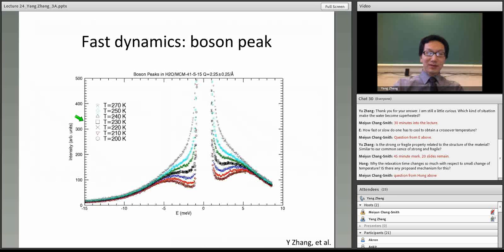Another interesting phenomenon that happens above the glass transition temperature is the so-called boson peak. For many crystalline materials, the phonon density of states g(ω) follows ω squared. So if you divide g(ω) by ω squared, you should have a straight line. For many glassy materials, if you measure the phonon density of states, you'll see a bump, the so-called boson peak. If we do incoherent neutron scattering, what we can detect is S(q,ω), the dynamic structure factor. In the small q limit, S(q,ω) is proportional to g(ω) divided by ω squared.